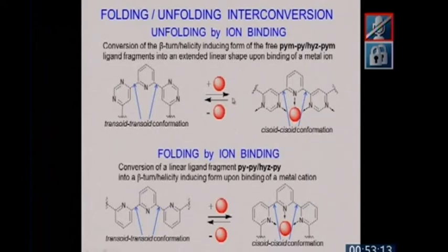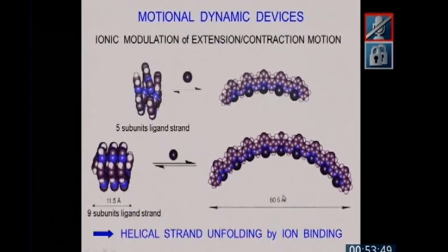Conversely, one can also imagine a sequence of pyridines which, when you oppose the nitrogens' direction, is necessarily a linear molecule. Then, when you bind a metal ion, this should turn around and give a curved, bent molecule. So by these 2 ways, here you go from a helix to a linear strand, and here you go from a linear strand to a helix. Can we see that? Indeed, and I haven't time to get into details. Let's look at the first case.